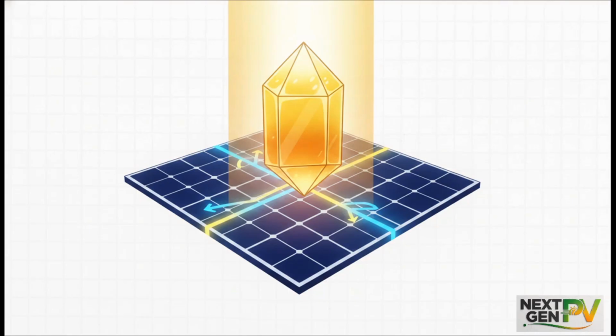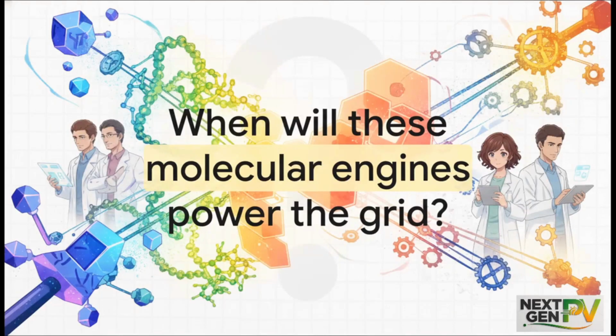Even with the toxicity concerns, lead-based compositions just possess this magical, almost irreplicable combination of traits. Direct optimum band gaps, sub-micrometer absorption, crazy long carrier diffusion lengths, and that unmatched defect tolerance. Plus, because you can tune their band gap, you can stack them directly on top of traditional silicon to create ultra-efficient tandem solar cells. The rapid evolution from simple, highly unstable crystals to these wildly engineered, moisture-resistant hybrid structures is easily one of the most exciting scientific journeys happening today.